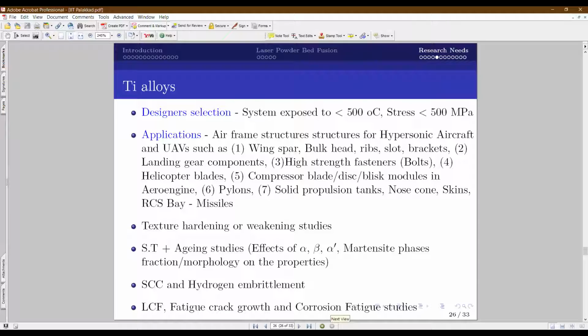And in certain environments titanium alloys are prone to hydrogen embrittlement and stress corrosion cracking. So you can look at that area. And most of the titanium components in aero engines undergo low cycle fatigue. So studies on fatigue, fatigue crack growth, or corrosion fatigue are very, very important. The data are currently not available. This puts a serious restriction on certification agencies or development agencies in selecting these alloys for fatigue critical applications.